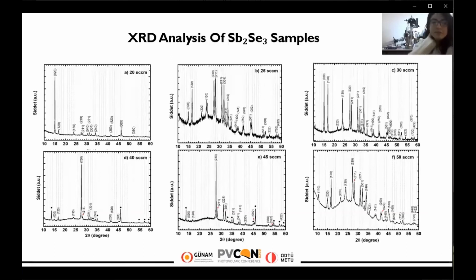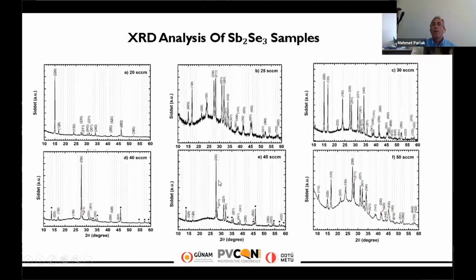Regarding these orientations, when we analyzed the six graphs, the sample grown with 25 SCCM argon has reached the best results. You see other samples. For example, if we look at the sample grown with 45 SCCM argon, the HK0 plane orientations are dominant. And these dots show antimony oxide phases. Here you see the dots, and they exist in the samples grown at 30 SCCM and above.